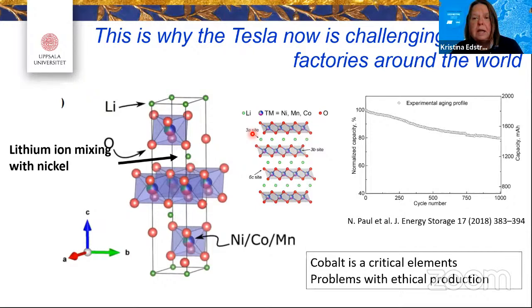So this is why Tesla is now challenging the gigafactories around the world. Can we easily remove this cobalt? Because one problem with the NMC materials is that you have these layers of lithium, and you have slabs of the oxide, and you have a risk of having the lithium ions and the nickel ions intermixing when you make this synthesis. So you always end up with a little bit of nickel blocking the pathway for the lithium transport. So that is one issue. Another issue is that you need the cobalt to really stabilize the structure. It's even worse when you take out the cobalt.